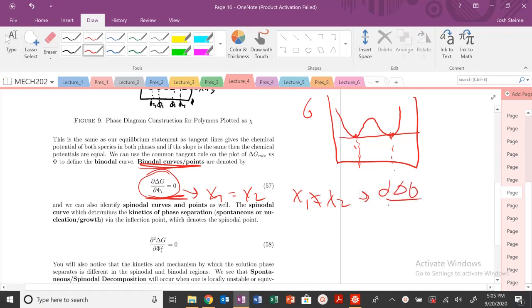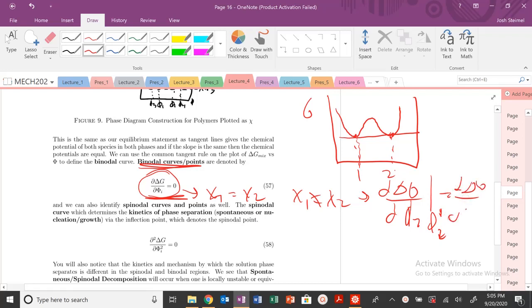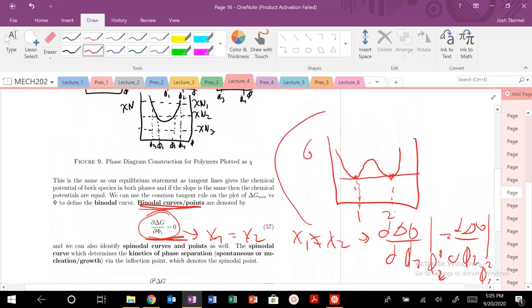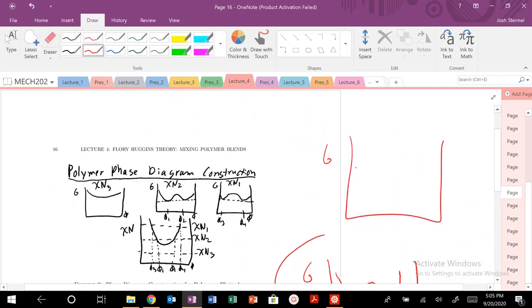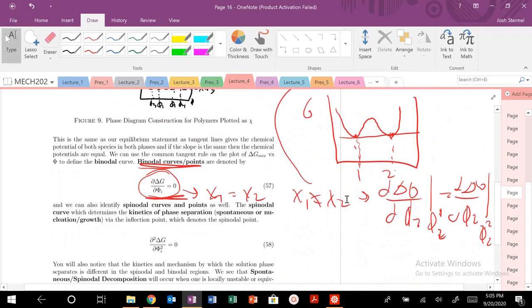We return to the expression for chemical equilibrium. Our slope at point 1 is equal to the derivative of ΔG evaluated at point 2 — basically saying the common tangent at points 1 and 2 must have equal slopes. In an asymmetric system the slope connecting those points is definitely not zero. That is where we're going to find our binodal points.